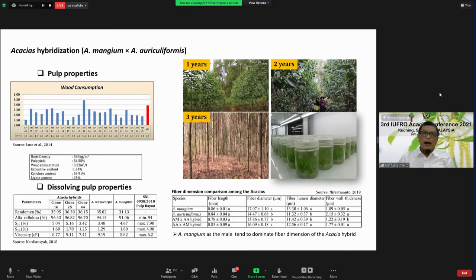And for Acacia hybridization, the Acacia hybrid between mangium and Acacia auriculiformis, we already improved the growth that I mentioned just before, 70% higher than our second generation mangium. But we also observed the potential of pulp property. For some of the clones that we already tested, the wood consumption is around 3.5 to 4 cubic meters of wood per ton of pulp. Not only pulp property, but we also observe the potential dissolving pulp property.